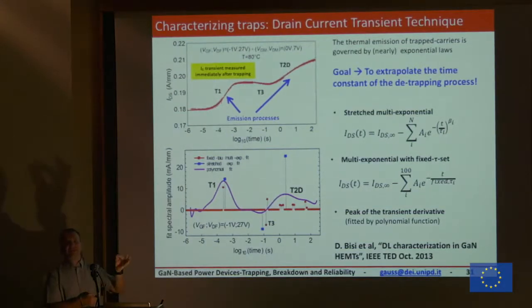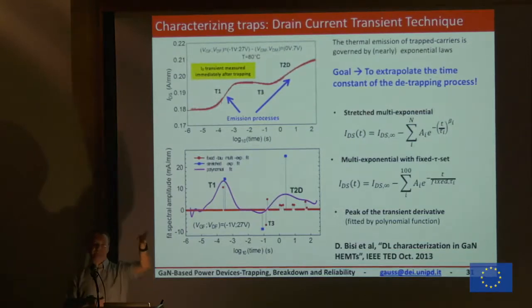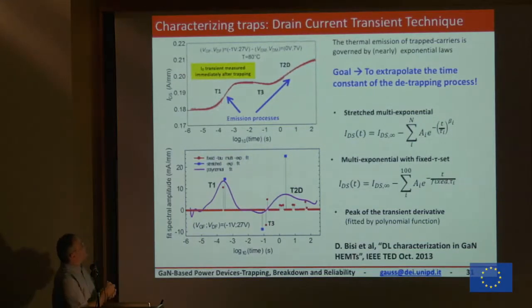The transient is related to the physics of the detrapping of electrons from traps. So here we know that there are some traps that at this time constant, 10 to the minus 4, are releasing the electrons. And this is the time constant, 10 to the minus 4, 10 to the minus 3. And when the electrons are released, the current partially recovers. Then we have traps that are going in the opposite direction, because we are having another trapping condition here, or traps that are trapping not electrons but holes, or vice versa. So the trapping of holes instead of electrons. And then we have other traps that are releasing electrons on a much longer time scale. This is seconds, 10 seconds or 100 seconds.